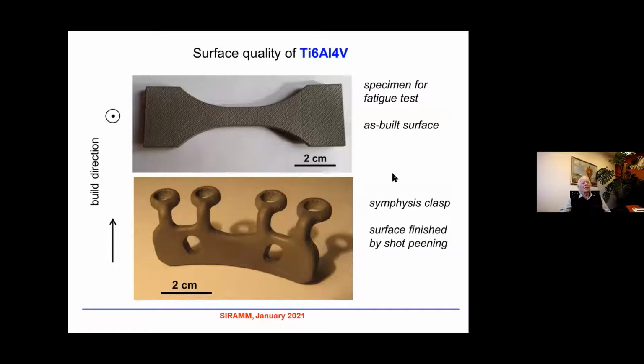Naturally, such a surface should be somehow improved. For example, for components which are used for healing of implants for the human pelvis, you can see here a symphysis clasp, the surface of such a component has to be improved. Namely, in this case, the improvement was made by shot peening. Nevertheless, you can see that the surface is not completely flat.